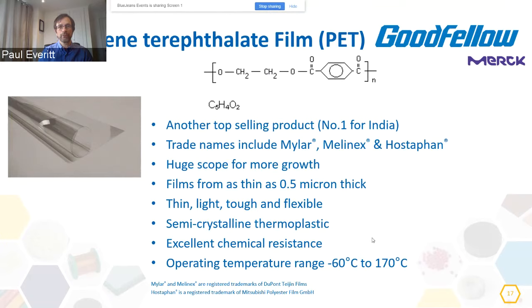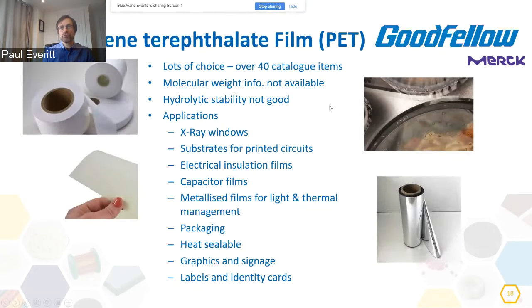We got that from the horse's mouth from DuPont Teijin, because the chemicals traditionally used in the past have been banned for a number of years because they're just pretty nasty. We have an operating temperature range, not quite in the realms of Kapton, but minus 60 to 170 degrees C, which is pretty good. Even if you think about food packaging, it has its place. There is a lot of choice. We have over 40 catalogue items, and as I said, molecular weight information isn't available. Hydrolytic stability isn't brilliant. You can steam sterilize it maybe once, a couple of times maybe, but it will cause failure of the material as it breaks down.